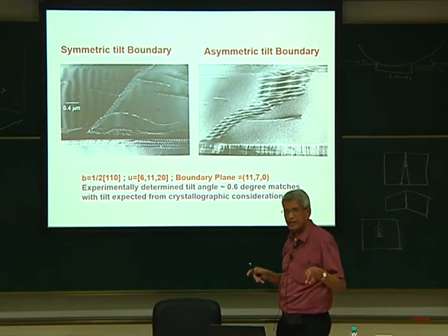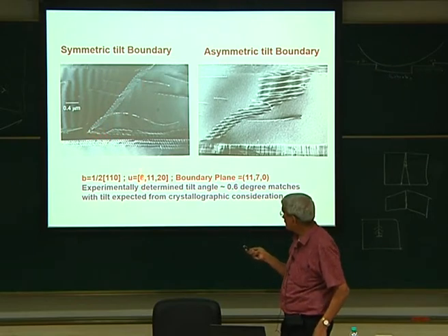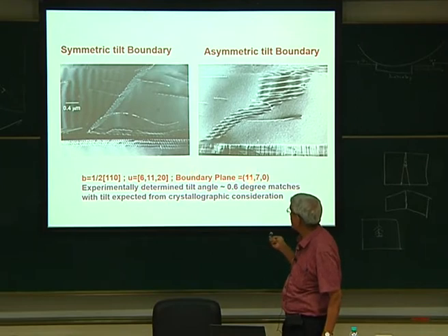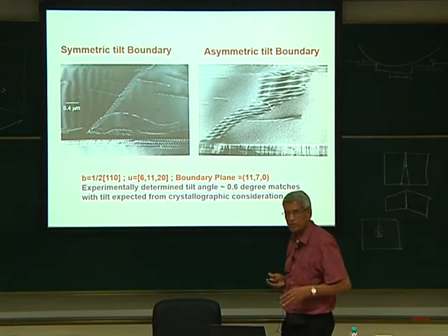As I had explained, to fully characterize the dislocation, we have to use the G dot B invisibility criterion, and then using stereographic projection, one has to find out the line direction and the fault plane. That's what has been done. And then we know what the dislocations present are, and the spacing between them could also be determined from this micrograph.